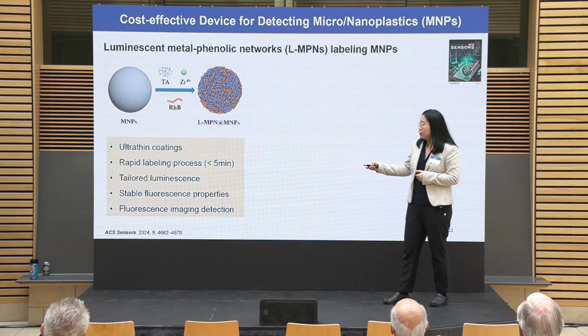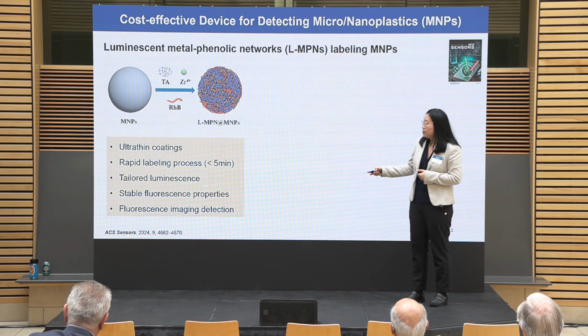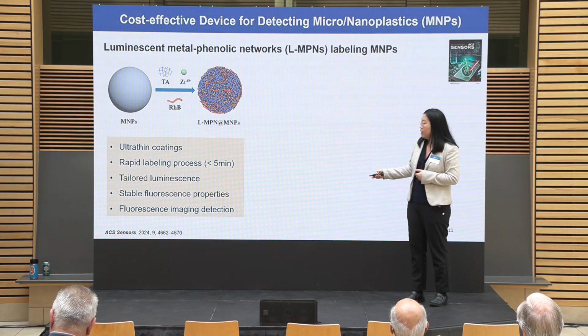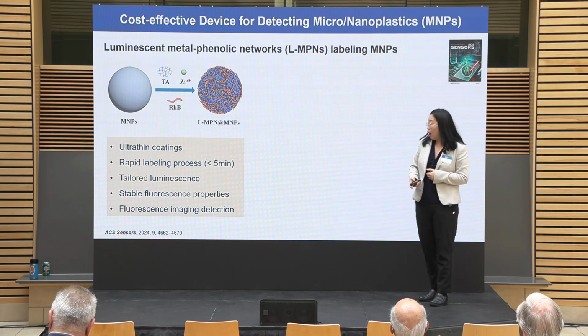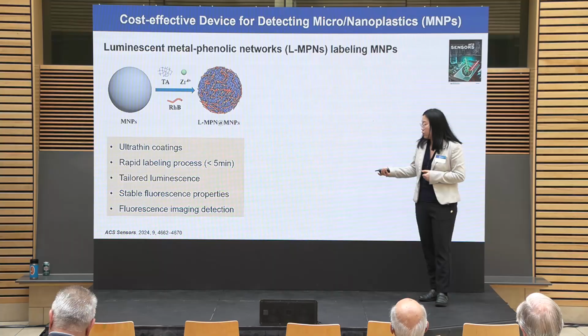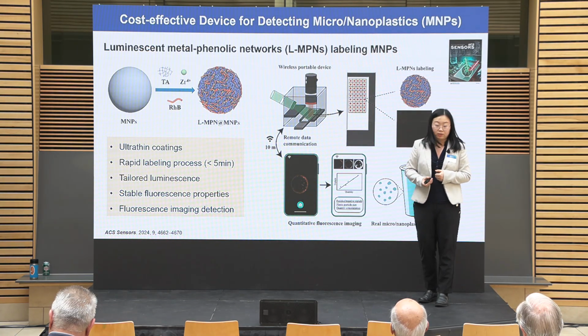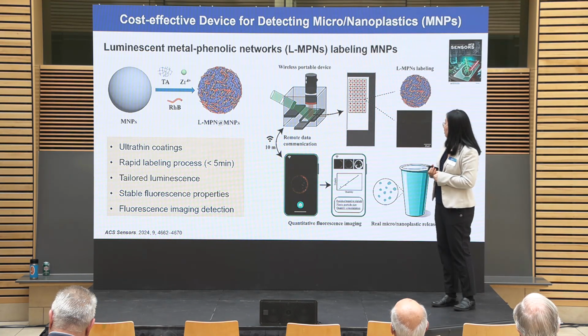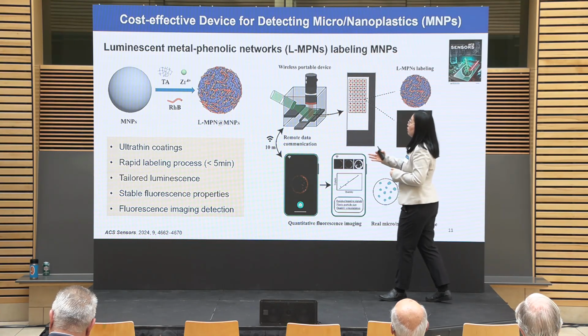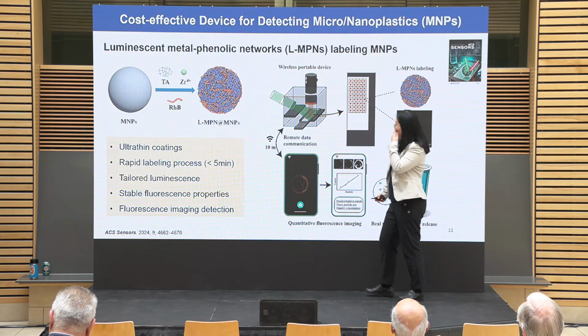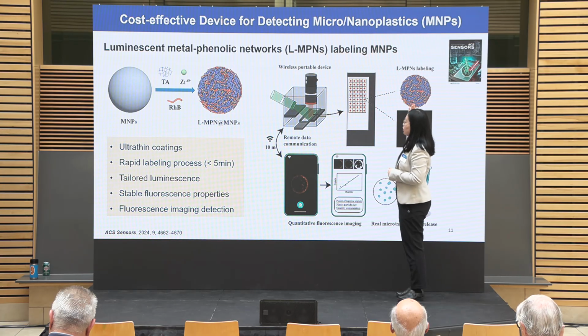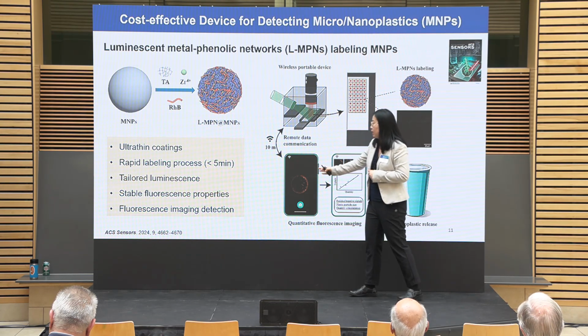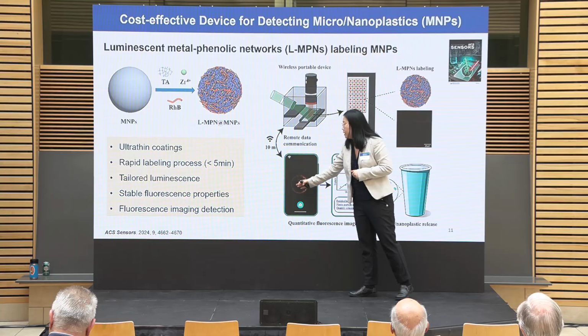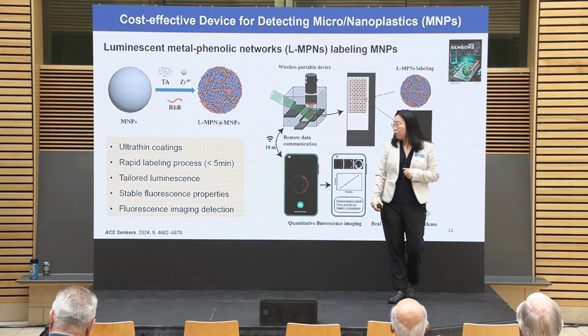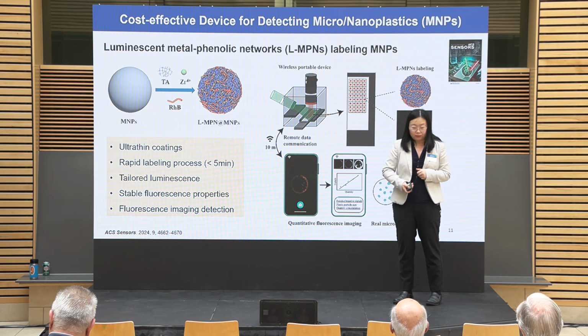It shows ultra-thin coatings, and the labeling process is very quick. We can also change the dyes to tailor the luminescence properties. It also shows very stable fluorescence signals that allow us to do imaging analysis. Here, we developed a portable device connected with our cell phone. This portable device is fluorescence-based, and we can image the coated plastics into a fluorescence image, and we correlate the fluorescence image pixel area with the quantity of micro and nanoplastics.